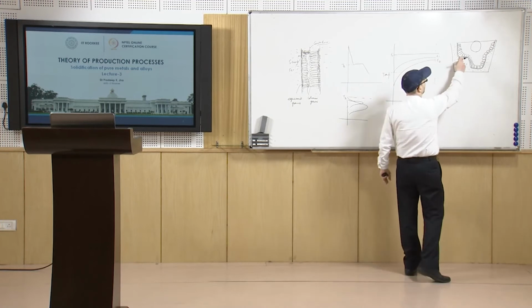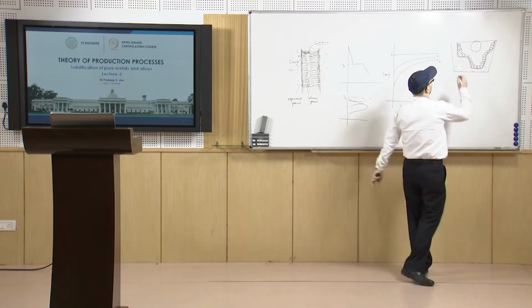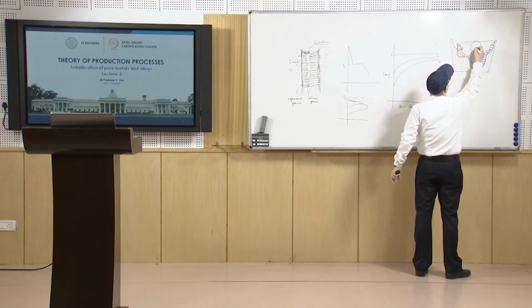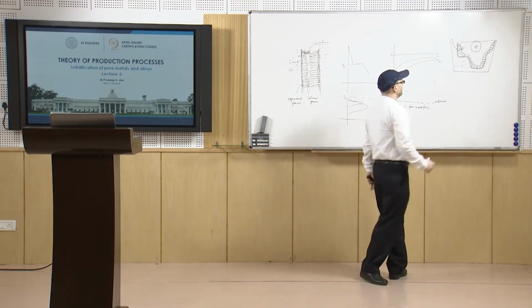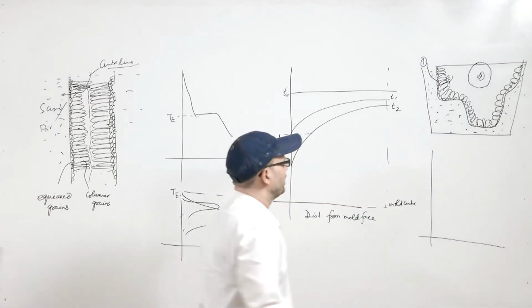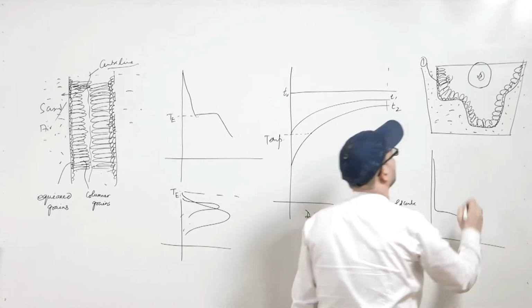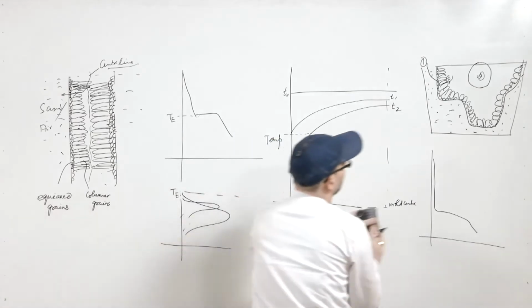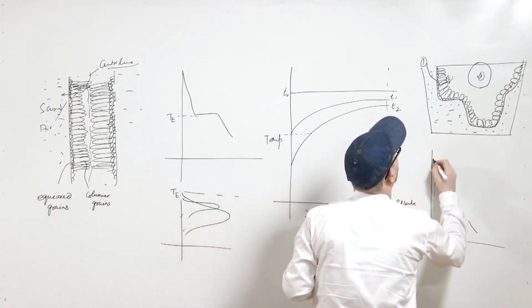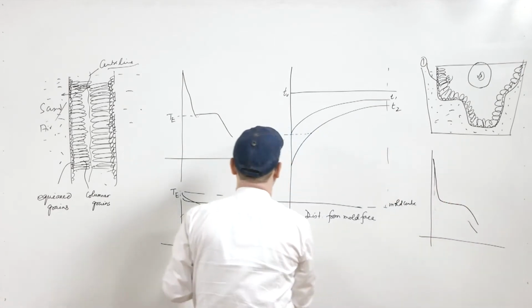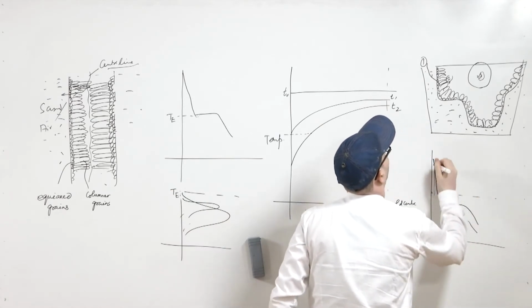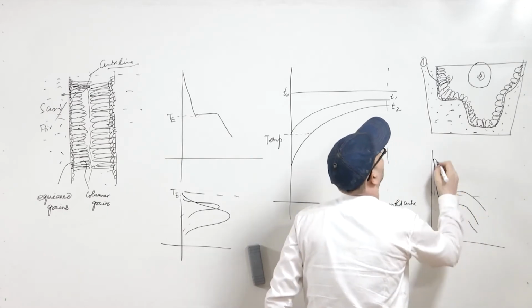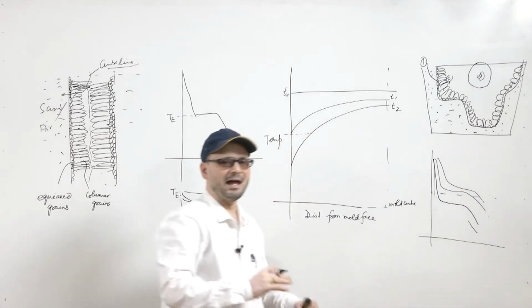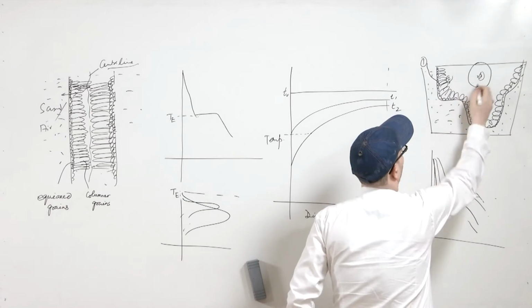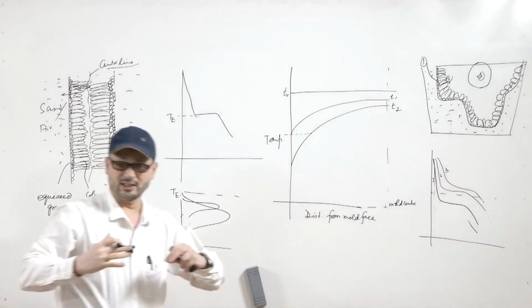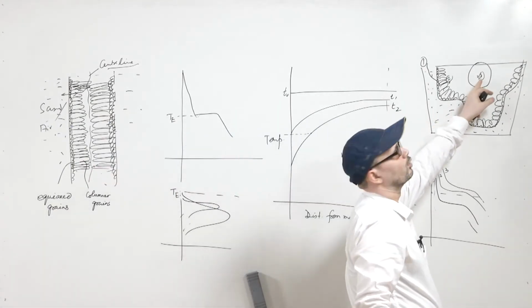Now if you look at this temperature, the temperature drop will be quite fast at this point. So if you take this point as 1, this point as 2 and this point as 3, what we see is that normally the temperature drop, if you look at the cooling curves, at the first point it will quickly go down, and then it will go like this. And similarly, suppose this is the equilibrium temperature, second point will come and then it will go like this, third will come and then they may go like that. So this way you have the delay, this is the second point and this is the third point. So you see that the temperature in this region is more and more, it is solidifying in the end.